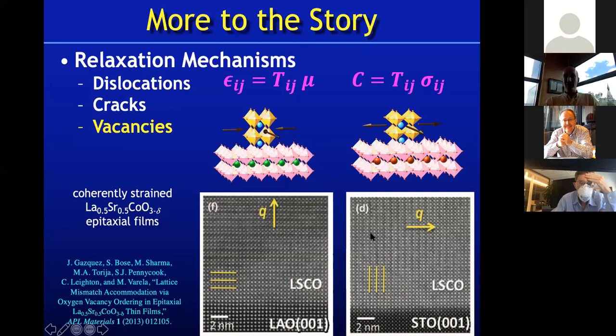Now, the defects are indicated by these lines. These lines, according to these authors, are oxygen vacancies that have come in as planar defects. And you can see that in the case of strontium titanate, where the material is in biaxial tension, those oxygen vacancies have aligned, again, in a biaxial way, as planes to accommodate, through defects, the change in the lattice constant between the substrate and the film.